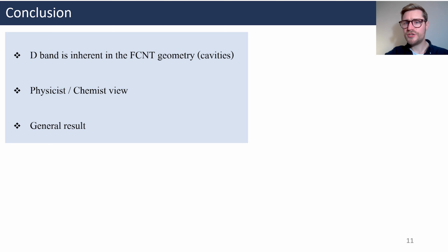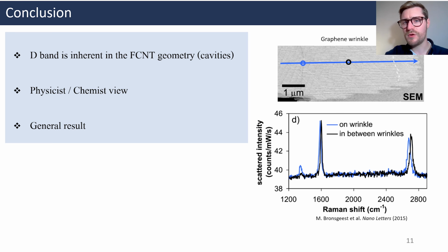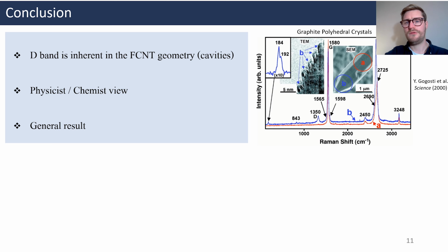Finally, what I showed you today is general. Usually used as a tool to quantify defect density in graphenic structures, the D-band cannot be used as such in the presence of a graphene fold. To illustrate this, I can take the example of graphene wrinkles. We can clearly see here the contribution of the wrinkle to the D-band. A second example could be the case of graphite polyhedral crystals. Here, a D-band is visible only on the zones where a curvature change is present.